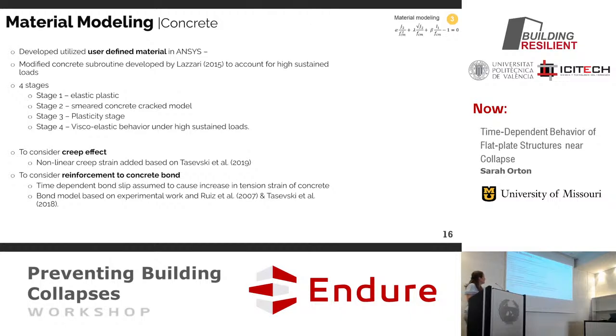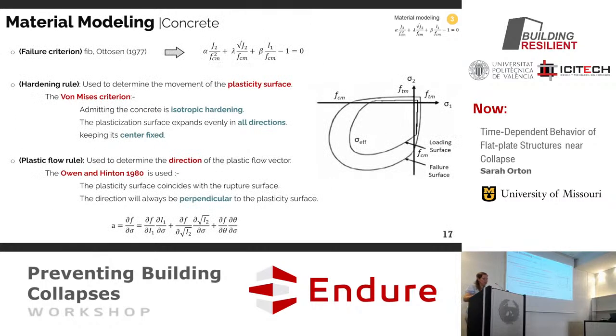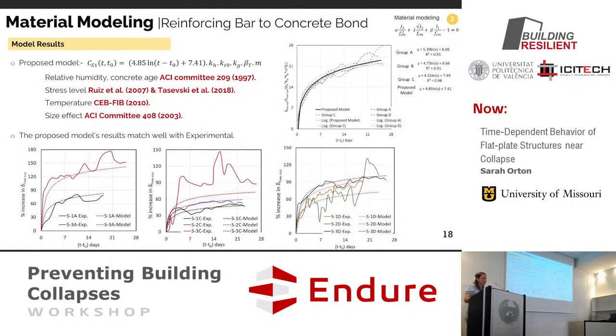And then for our bond model, we based it on some of the previous research and then applied it to our own data. Did some failure criterion, applied a hardening rule, applied a plastic flow rule. And then for the bond model, we took some existing bond models and then looked at our data and were able to fit an equation here. And these coefficients 4.85 and 7.41 were coming from the best fit from our equation. And so that allowed us to predict the bond slip.